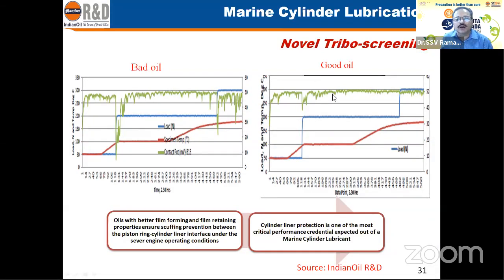On the contrary, see the good oil, where initially there might be some furrows, but fairly the film is constant, which clearly indicates that, because this is a hydrodynamic regime, definitely the film thickness of the lubricant matters, and also it's a once through system. So lubricant is injected in microliters, and the film has to form, and it gets evaporated, and a fresh film has to be replaced. So in such a complex scenario, maintaining a uniform film is very important. We could very accurately predict by this tribo screening.